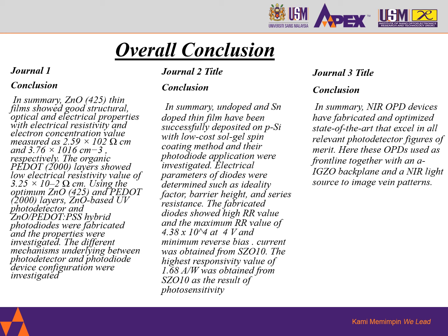per cubic centimeter respectively. The organic PEDOT layer showed a low electrical resistivity value of 3.25 × 10^-2 ohm centimeter. Using the optimum zinc oxide and PEDOT layers, a zinc oxide based ultraviolet photodetector and zinc oxide PEDOT:PSS hybrid photodiodes were fabricated and the properties were investigated. The different mechanisms underlying the photodetector and photodiode device configurations were investigated.